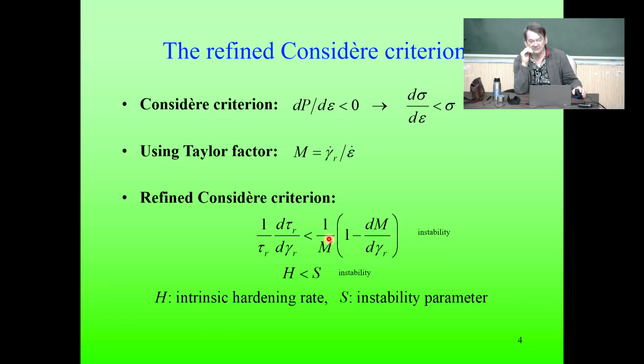There are a number of experiments you can do, for example, with a zinc single crystal. If you make it and then begin to pull, it deforms to very large strain in single slip. Not small strain, it goes to strains of 2 or even more. But what I couldn't understand is if I have a stable orientation, then it is giving the highest instability parameter. Yes, because this is negative here, 1 minus. Anyway, dm by d gamma is 0. It's higher instability. This is the instability parameter. So if this is high, then you need more intrinsic hardening to have stability. It is basically an instability parameter: the higher its value, the more unstable your deformation actually is.